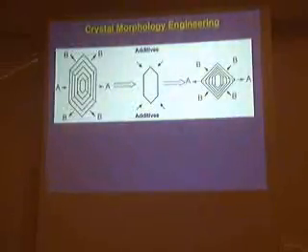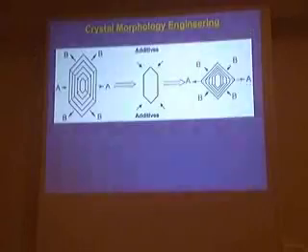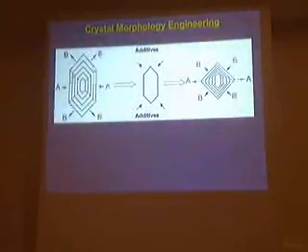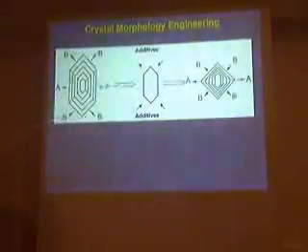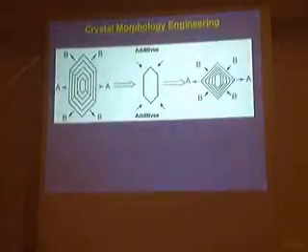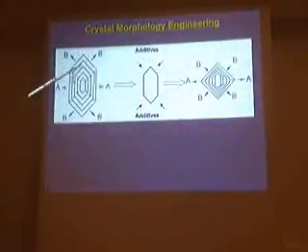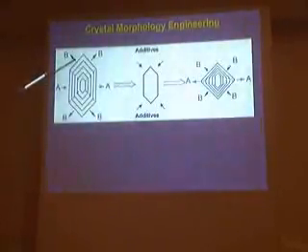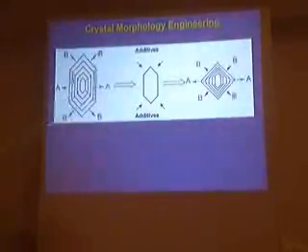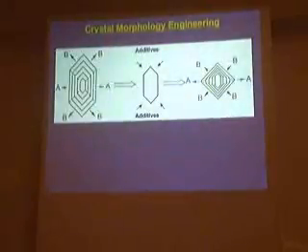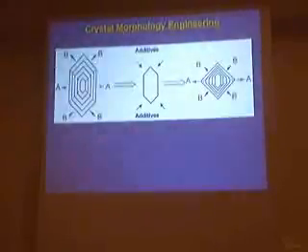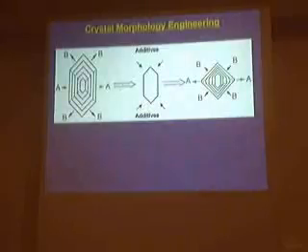And then we say the following. If you're dealing with organic molecules, which belong to space groups of low symmetry, like triclinic, monoclinic, or rhombic, then you have various faces that delineate these crystals. And therefore the structures of the non-symmetry related faces are different. And you can deduce the structure of these faces from the crystal structure of the system.